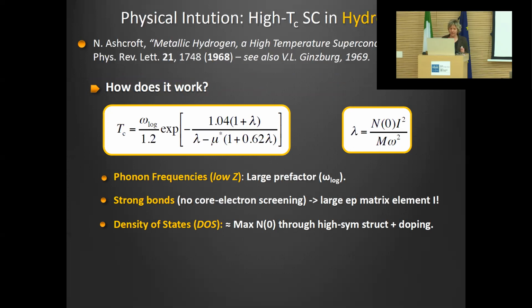This gives the critical temperature of a superconductor in terms of essentially three parameters: a phonon frequency, an electron-phonon coupling constant lambda, and a so-called Coulomb pseudopotential mu star. And if we think about hydrogen, there are basically three reasons to think that hydrogen would be a high-TC superconductor.